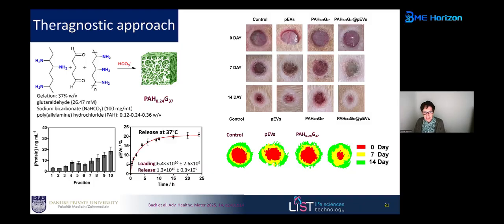They had diabetic wound ulcers on it, and we showed, by applying these bandages on them, that we get really high wound healing with our gels integrating these platelet-derived particles. So I think it's clear how this theragnostic approach will work. You will have the sensor which tells you there's an inflammation going on, and then we will trigger the release of these platelet-derived particles to the wound to have healing.